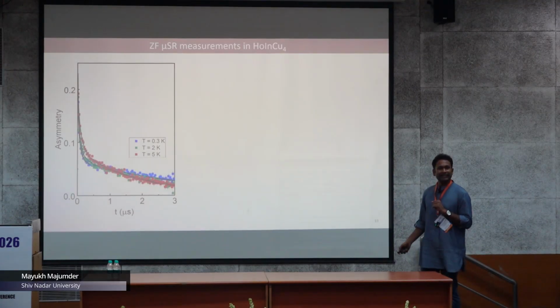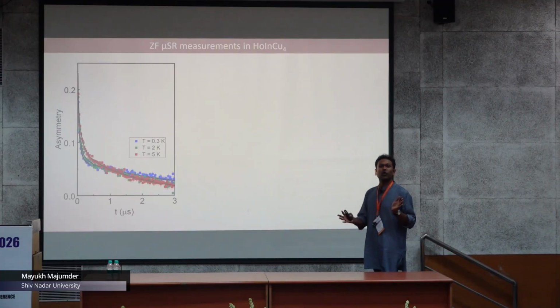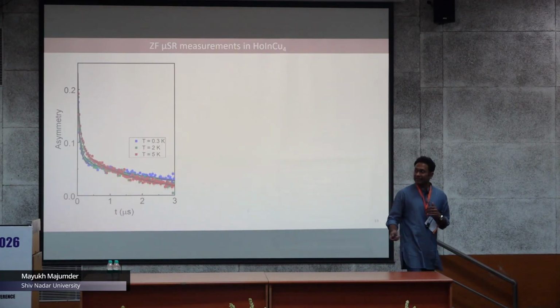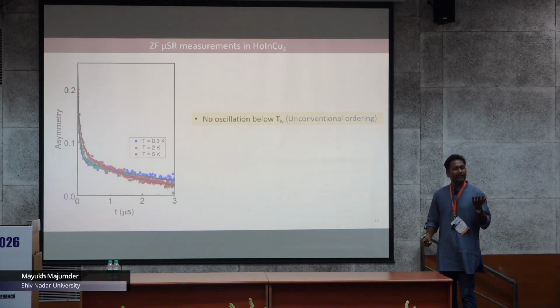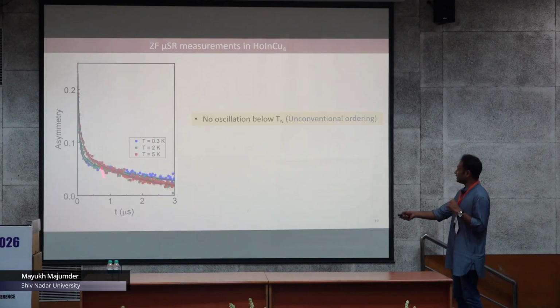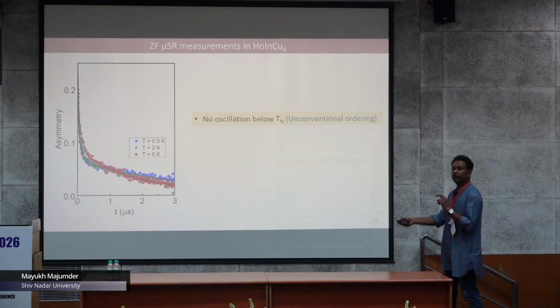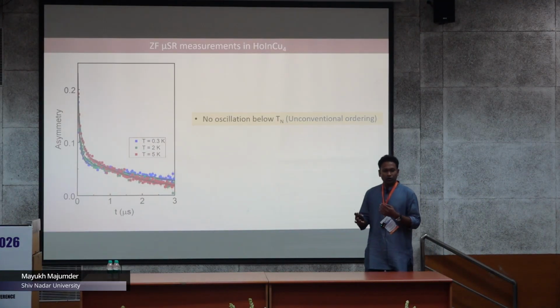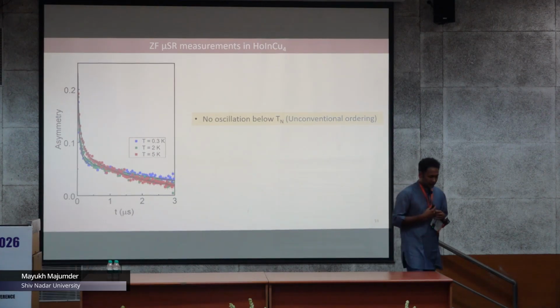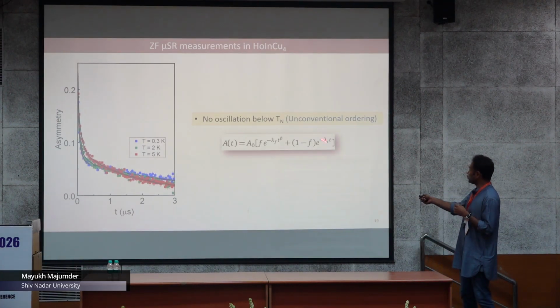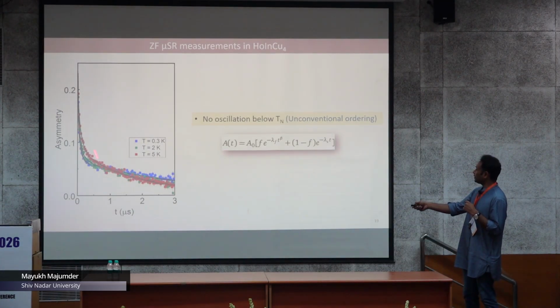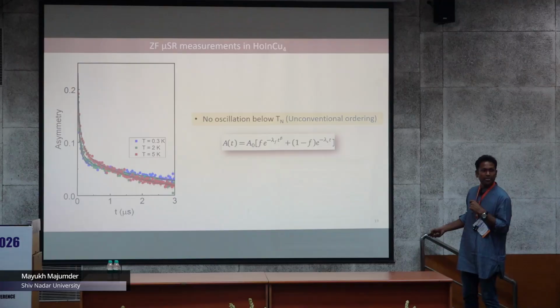So if you look at the zero field spectra, you directly can see that there are no oscillations present down to 300 millikelvin, indicating that there is no long range magnetic ordering, again indicating that this is rather a complicated or unconventional type of ordering. And you can easily see from the asymmetry also, you need 2 exponentials in order to deconvolute the asymmetry, and we use this kind of function. And one of the lambda or the relaxation rate was found to be fast, we denoted it by lambda f. One was slow, we denoted it by lambda s.